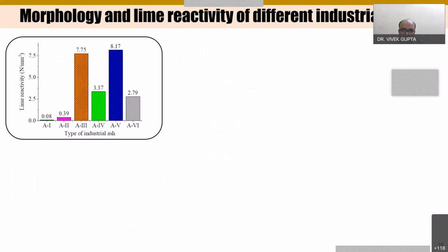Like we have observed the highest lime reactivity of 8.17 Newton per mm square in the A5 ash, and the second is the A3 ash. And you can see although A6 ash has a very good LOI value, still the lime reactivity is very less due to the presence of inherent minerals. And then we have also